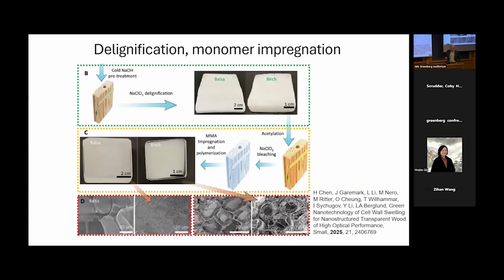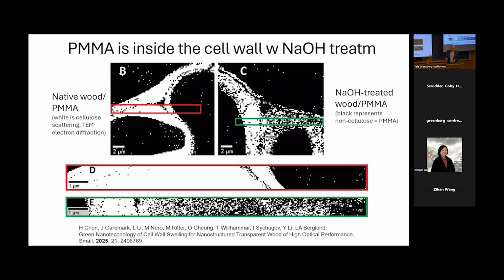And what we did was that we filled this, we prepared samples successfully. We did chemical treatment and filled with a polymer. If you look at the images here, you can note that the cell wall is swollen, and we are able to remove some of the optical defects that can otherwise cause problems with transparent wood. And this is the proof. This is electron diffraction. On the left-hand side, you have native wood and PMMA. On the right-hand side, we have the specially treated composite. The dark regions mean that we have impregnated the cell wall with the polymer. So we have a nanoscale composite by using this procedure.